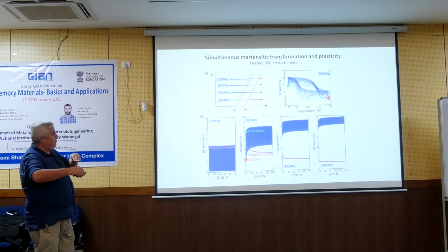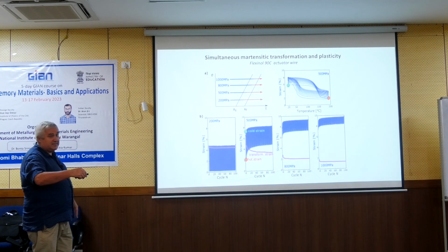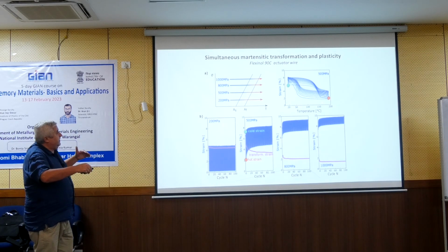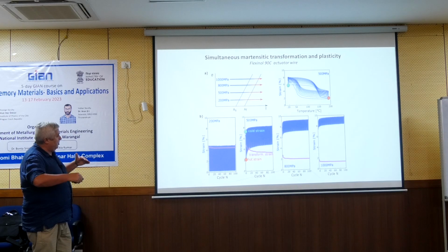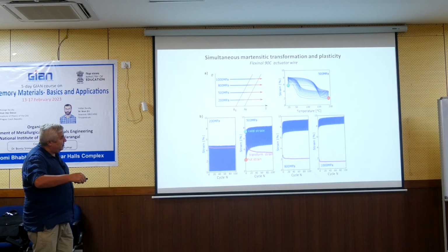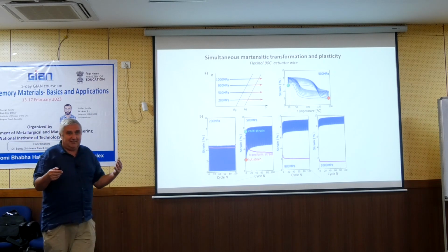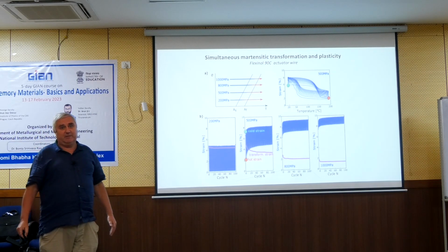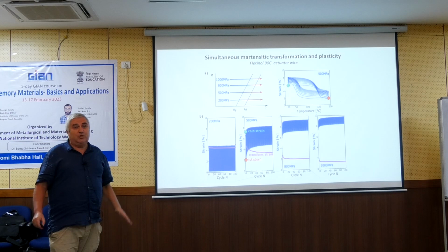You don't decide about this; the amplitude is set by the sample. We are always cycling. We are heating the wire above Af, and then it cools, and then we heat and cool, and you get such kind of oscillation. But what will be the amplitude? This is the outcome of such an experiment.